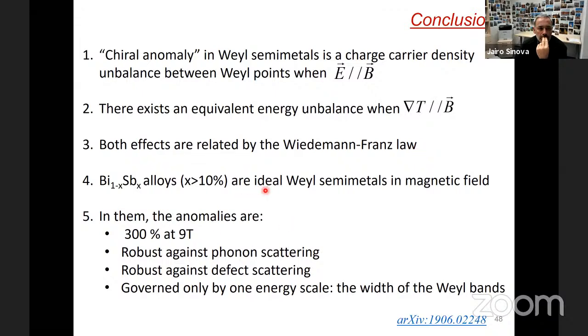I hope to convince you that the bismuth antimony alloys are ideal topological insulators at low field and ideal Weyl semimetals in the high magnetic field along the trigonal direction. And I hope to have convinced you that we have seen a thermal version of the chiral anomaly. It's very large, 300% of the electronic part. It's robust against phonons, it's robust against defects, and it's governed by only one energy scale, and that is the width of the Weyl bands. Thank you.